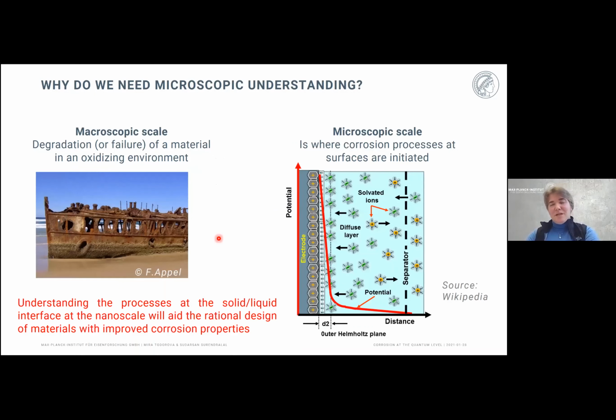So why do we need to understand the microscopic scale if we actually observe and see this failure of materials at the macroscopic scale? When you zoom in closer to the interface, you will start seeing atomistic details. And what we know is that usually if water, let's say, comes into contact with a metal, they have different surface dipoles, and so there will be a potential drop. This will also be enhanced by the presence of ions that are solvated in the aqueous environment.